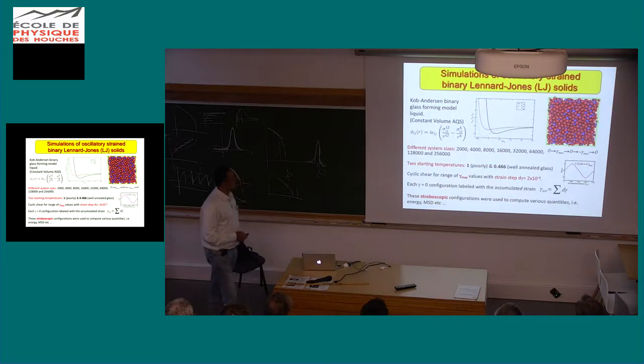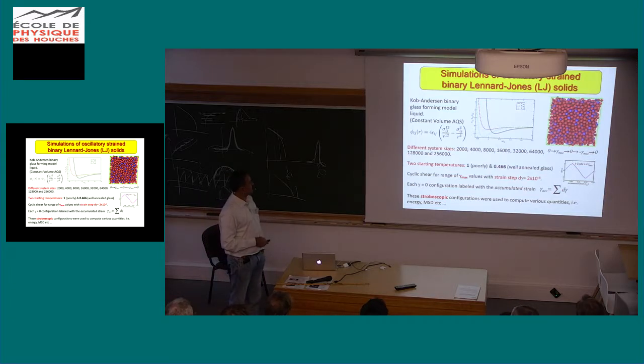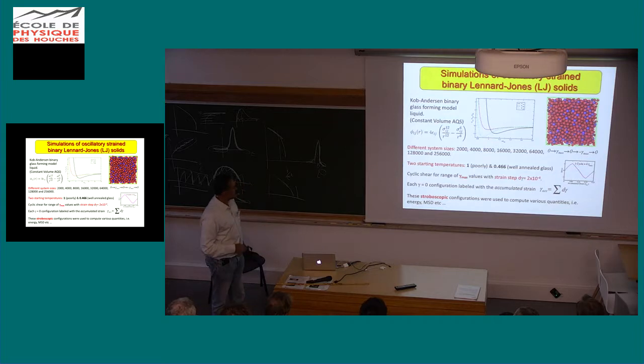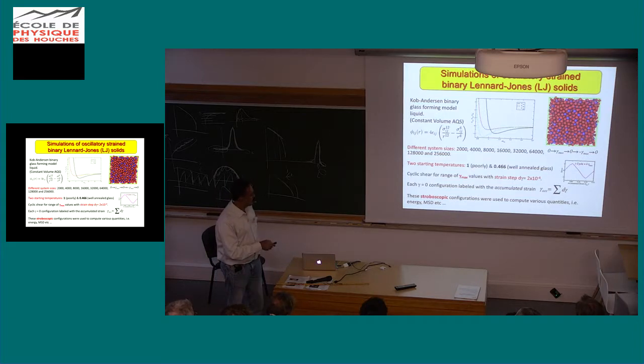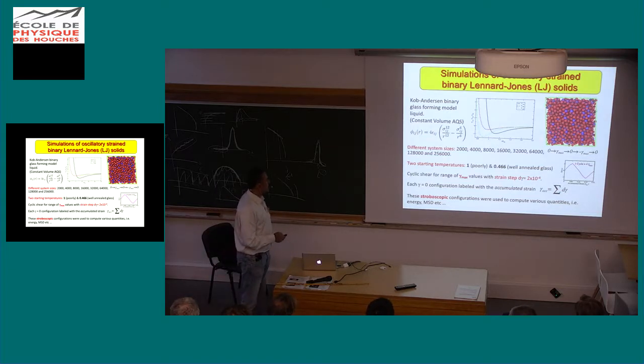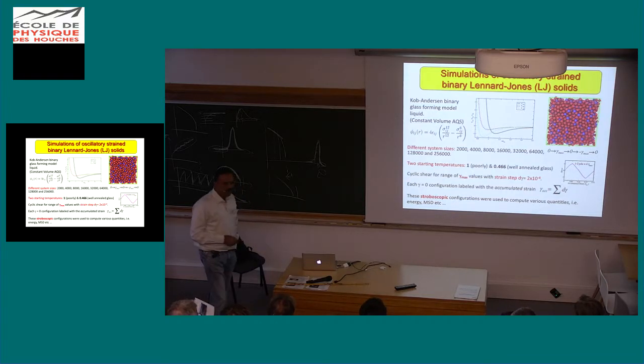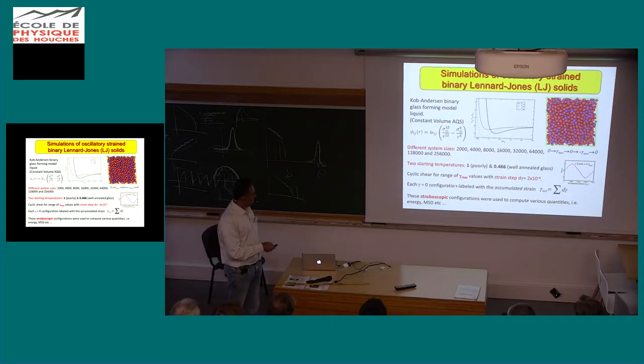Okay, so the model system we look at is a well-studied glass former called the Kob-Andersen binary Lennard-Jones mixture, and we study this over a wide range of system sizes. As I already mentioned, we start with liquid configurations at 2 different temperatures, and we subject them to energy minimization to obtain the initial conditions for what we do. And the cyclic shear, as I said, is characterized by a maximum amplitude of strain, and we vary this between roughly 2% to 20%, and in small strain steps of 2 times 10 to the minus 4.